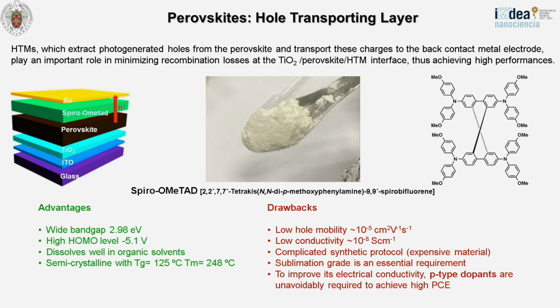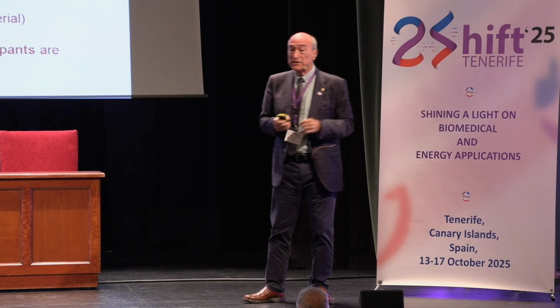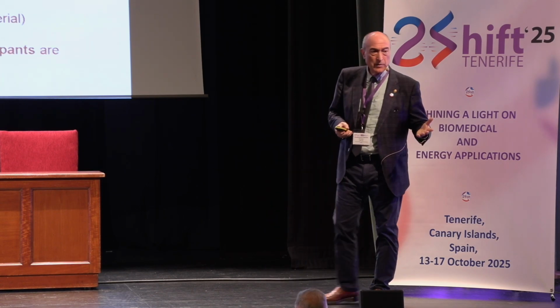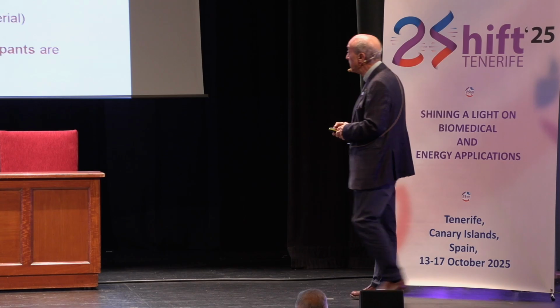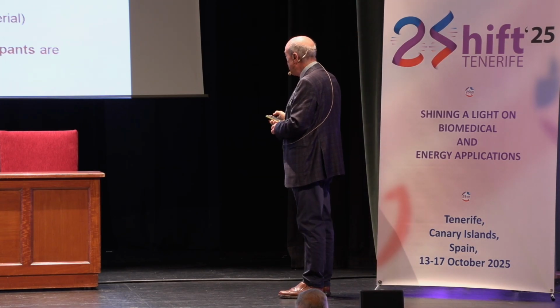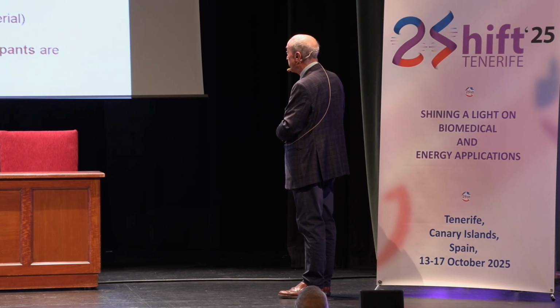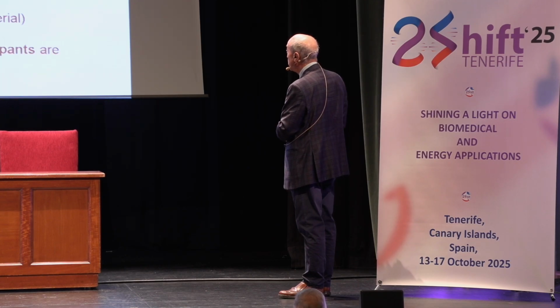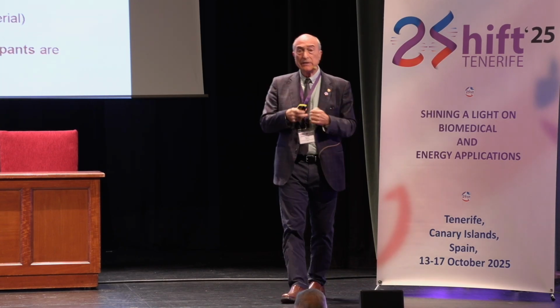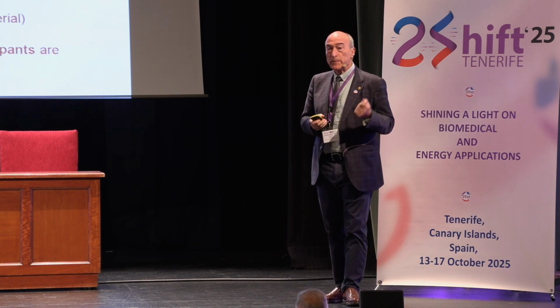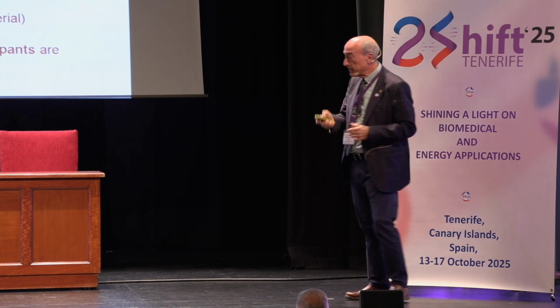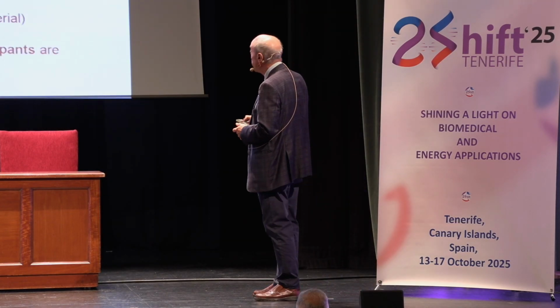Low mobility, low conductivity. The synthetic protocol is complex. And actually, you have to purify the material, because this is chemistry of materials, by sublimation. This almost prevents its use for practical purposes or industrial fabrication of cells. So, if you want to improve the conductivity, then you have to add dopants. With this, the cell is much better, but the problem is that the stability decreases drastically as well.